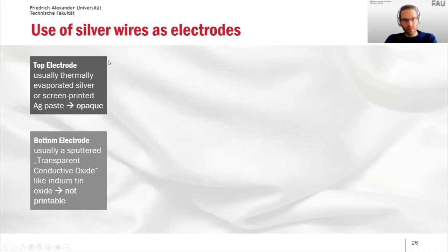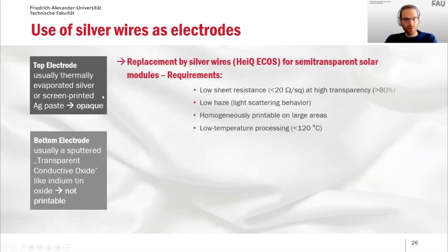So if we want to replace those electrodes with the silver nanowires from HeiQ ECOS ink, if we want to replace the top electrode in order to obtain semi-transparent solar modules, we need low sheet resistance values below 20 ohms per square and fairly high transparency because we want to look through the module. Also, the haze should be quite low because it should not only be translucent, but also we want to really have a clear vision through the module. So less light scattering as possible.